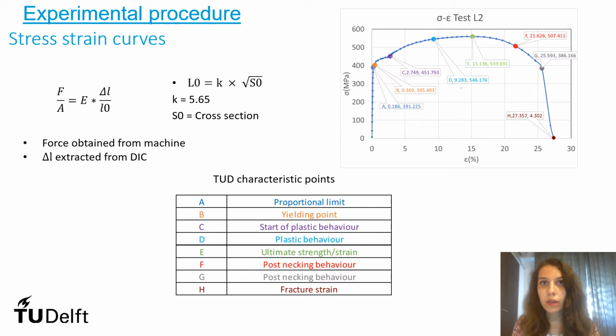For the stress-strain curves, I extracted 8 TUD characteristic points, which are the proportional limit, the yielding point, the start of the plastic behavior, leading up to the ultimate strength and strain. Point F and G are 2 points that describe the post-necking behavior and leading up to the fracture strain.